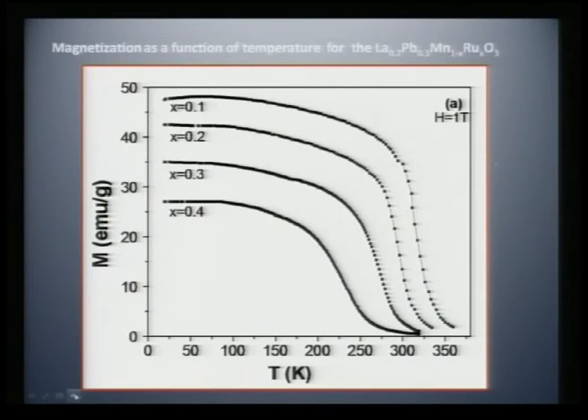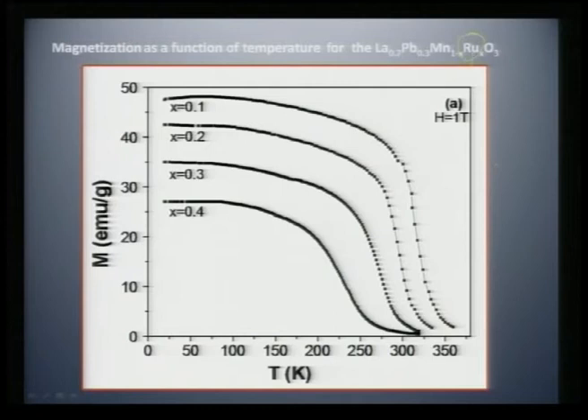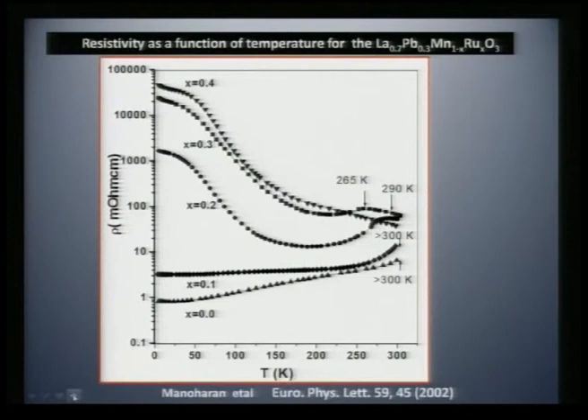And let me take you through another example also and show you. Suppose I substitute ruthenium in manganite, then keeping lead concentration constant, as a function of ruthenium concentration, you still see a very strong ferromagnetic loop. In other words, even up to 40%, I am seeing almost for every ruthenium there is a nearest neighbor manganese in such a unit cell, you would see a strong ferromagnetic transition happening. So, what is it that makes it important?